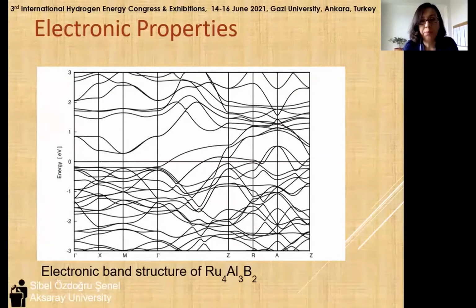The electronic band structure was plotted along the high symmetry directions of the first Brillouin zone, and the Fermi energy level was taken as 0. There appears to be no band gap. It suggests that the compound is metallic in nature. As can be seen from the graphics, the Ru4Al3B2 compound shows conductive character.